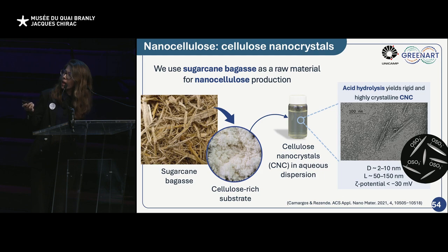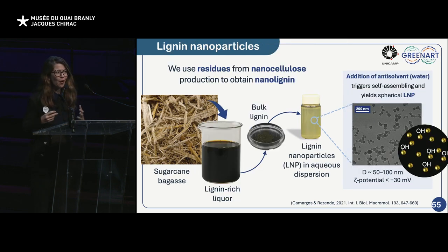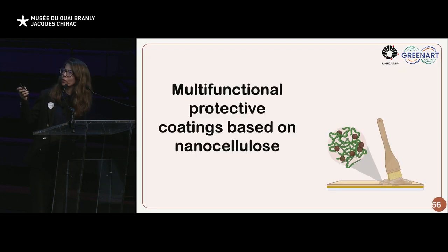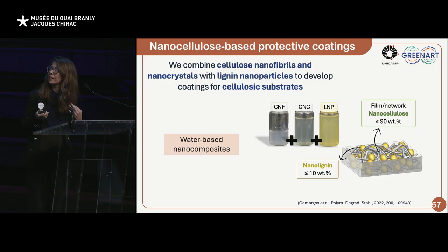On the other hand, with the residue of the cellulose processing, we obtain this liquid fraction. It's an alkaline liquid fraction rich in lignin, and then we can also convert lignin into nanoparticles, the lignin nanoparticles. And these lignin nanoparticles are obtained by solubilizing lignin, and then we add water as an antisolvent, and the lignin macromolecules self-assemble into these nicely shaped and beautiful spherical nanoparticles. And now we will discuss the protective coatings based on nanocellulose and lignin, and nanolignin.